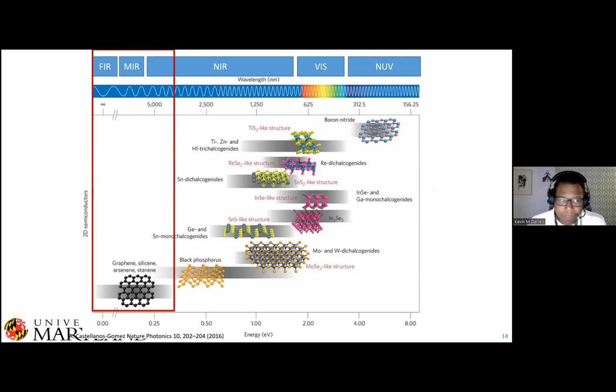And graphene surface plasmons, these are tightly localized electrons oscillating in collective motion. And this happens when you hit it with an incident electromagnetic wave. And so what we do is we take these micron-scaled graphene structures, and we're able to confine these oscillations and produce plasmon resonances in this terahertz range.